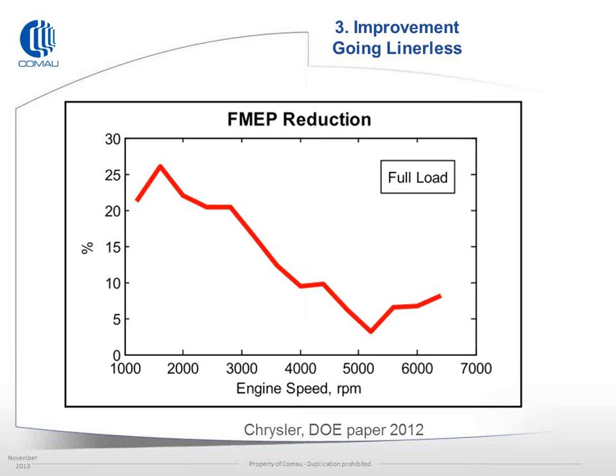Again, in the paper from Chrysler to the DOE in 2012, you can see they had an improvement of up to 27% in the low mean operating range, where you typically are with an engine between 1,000 and 2,500. This is significant. It contributes to about an improvement of 3% in a vehicle, which in this day and age is pretty hard to come by.